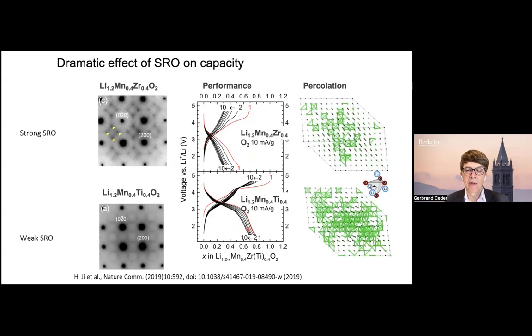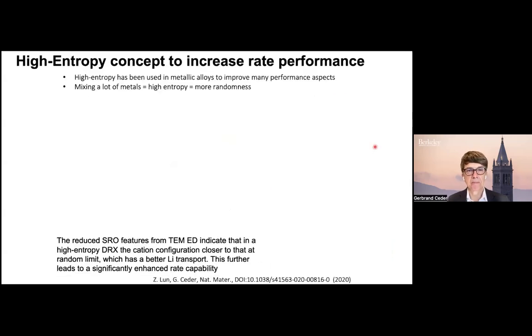And you can model that, and actually this is the percolation shown in the zirconium one, and this is in the titanium one. And as you see in the titanium one, the short-range order is much more favorable to make zero TM channels. So you have a lot more of them, so you have much better diffusion paths, whereas in the zirconium, you have these barely percolating diffusion paths, which is consistent with the poor performance.